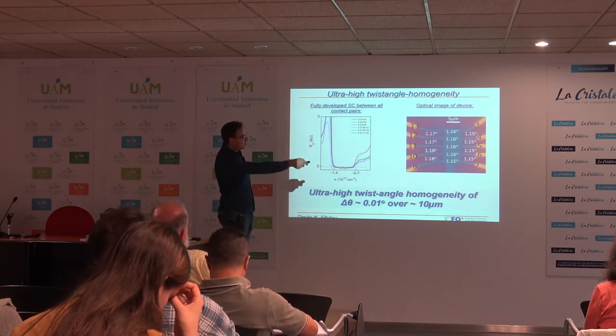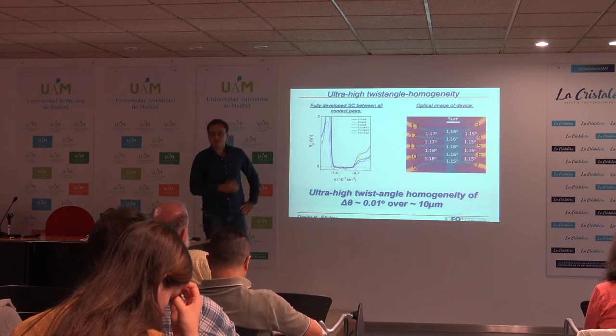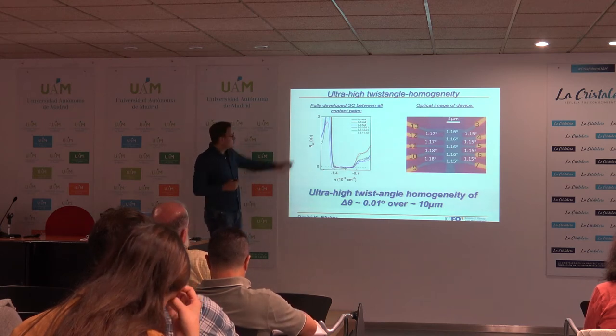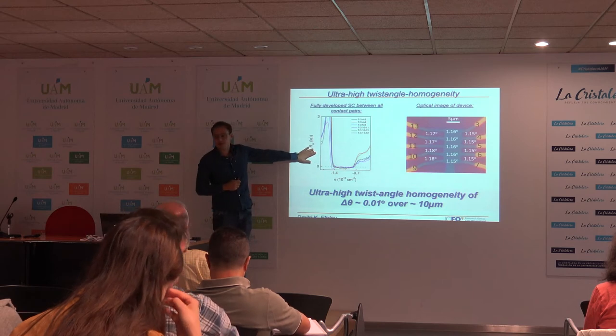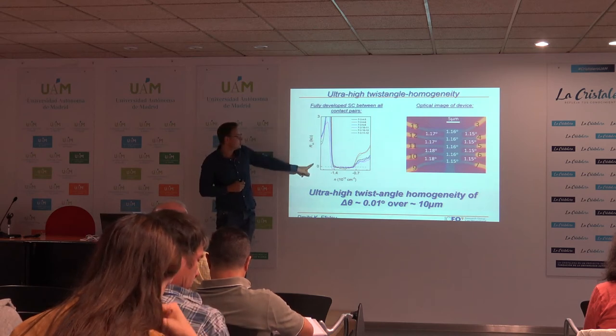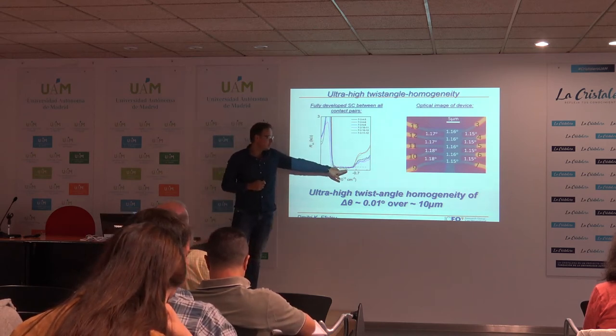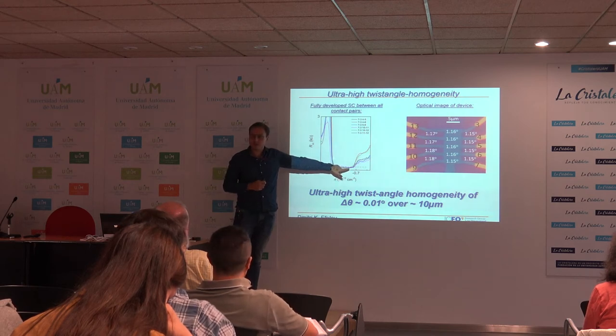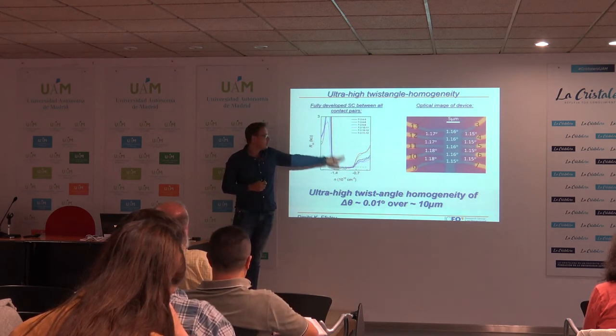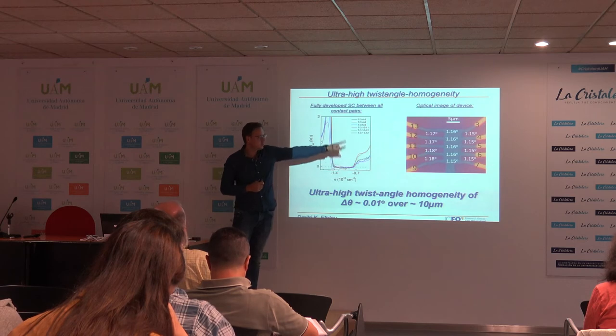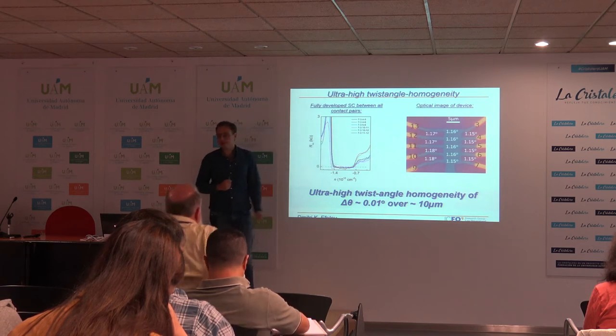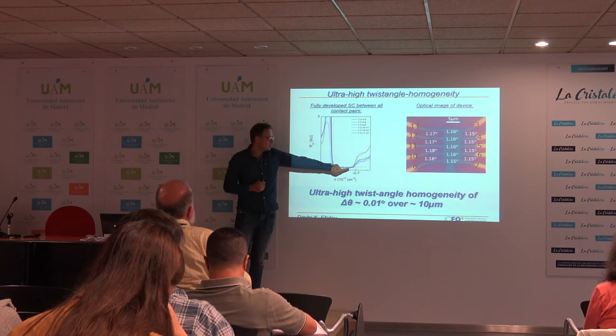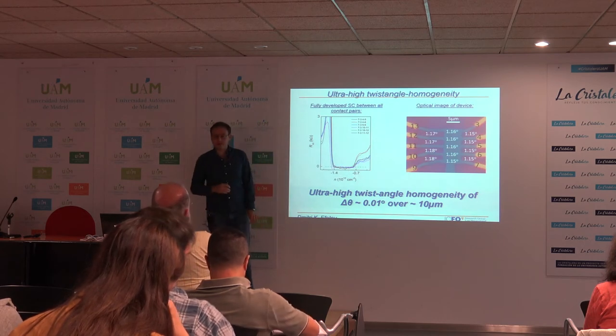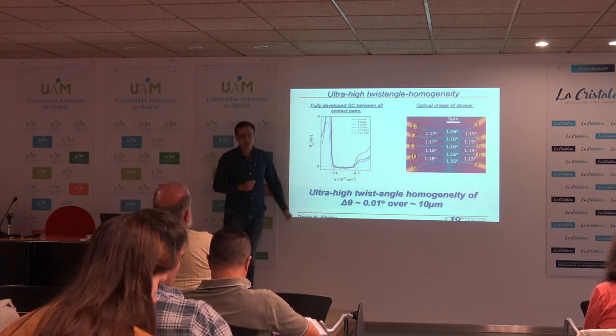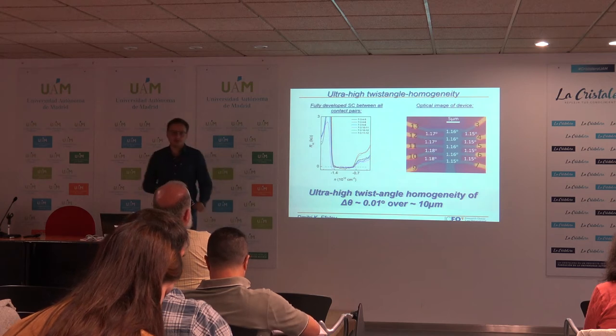Again, we get an extremely high homogeneity of twist angles all across the device. And this is a typical measurement of the superconducting state. This is resistance as a function of carrier density in the region where we see the superconductivity. All the different curves here are just using different contact pairs in the device. So really, across the entire device, without any phase separation, we see a macroscopic superconducting state everywhere in the system.